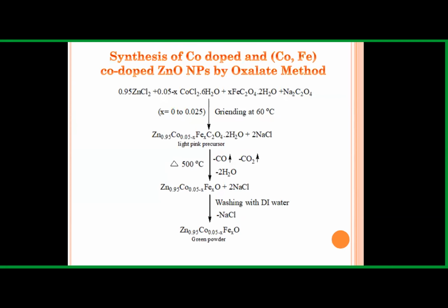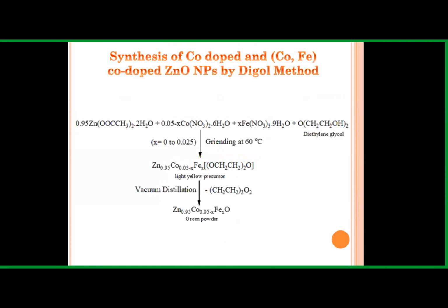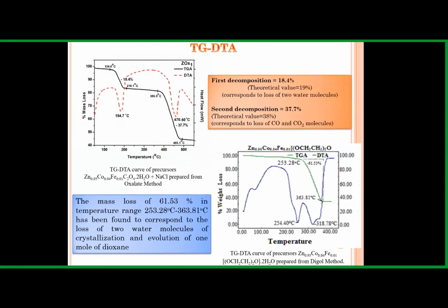In the first method, that is the oxalate method, we used sodium oxalate, and for co-doping, we used cobalt chloride and iron oxalate for iron, with zinc chloride as the starting material. Similarly, in the second method, we used diethylene glycol instead of sodium oxalate. In both these strategies, these are the TGA/DTA data.